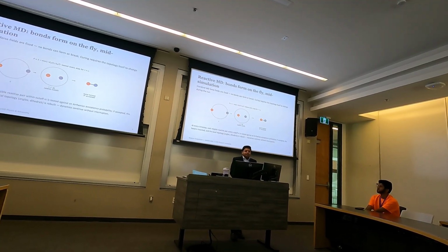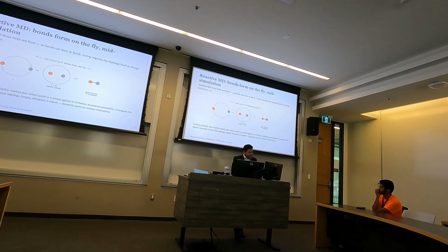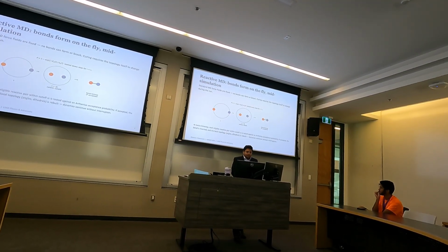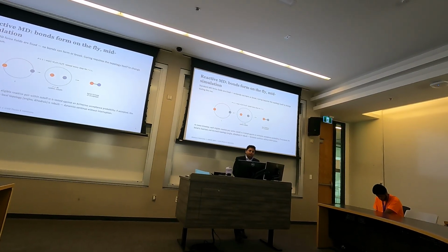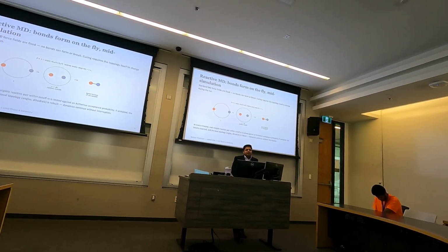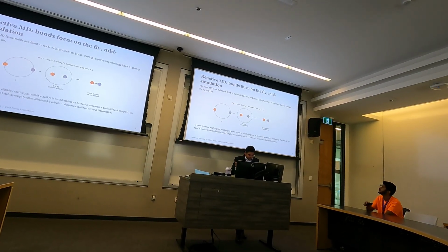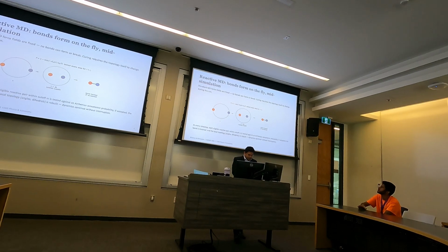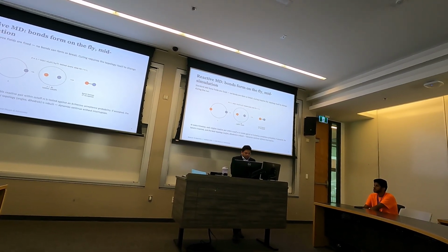Now, once we have the system equilibrated at that exact point that we want, we start with the reaction. In this particular simulation, we are using normal molecular dynamics, where the force fields are fixed, which means that the bonds cannot be created or broken, but we still want the bonds to occur in the experiment. So what we do is use an Arrhenius model here again.